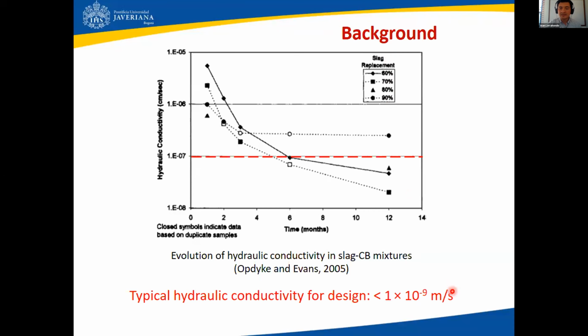So for design, typically the hydraulic conductivity of slag CB cutoffs is in the order of 10 to the minus 9 meter per second or less, which is basically the straight horizontal dashed line that you are seeing here in this plot.